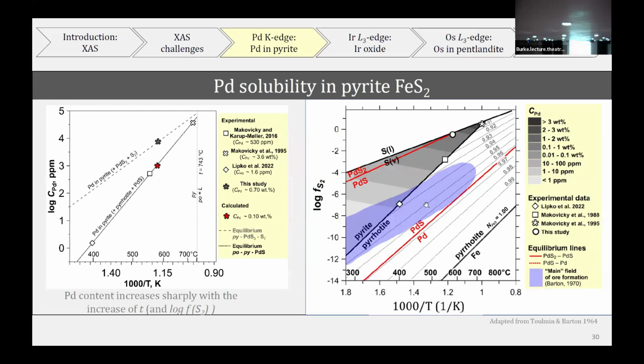So why? In order to answer this question, we plotted our data on the classical Toulmin-Barton diagram from the 60s. Our data is the solubility of palladium in pyrite, and we also plotted the nominal main field of ore formation. As you can see here, in most of the deposits on Earth, the sulfur fugacity won't be enough to produce palladium-bearing pyrite containing a few weight %, because it's here. So in most cases, we're getting the ppm level, maybe a few hundred ppm, like we see in nature.